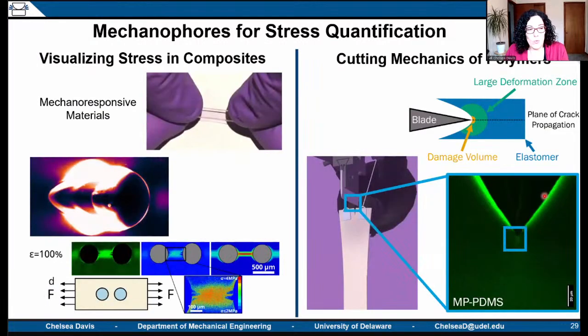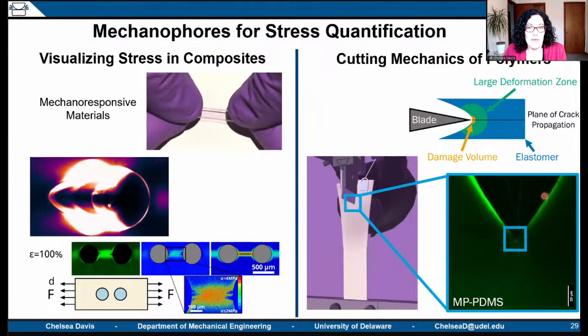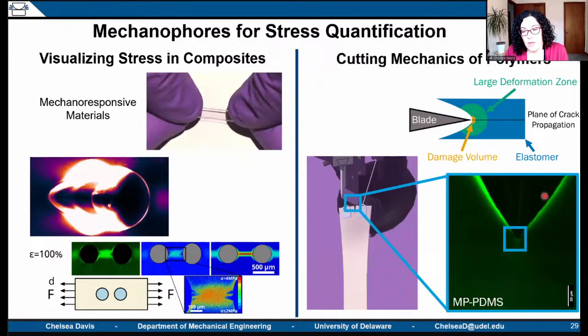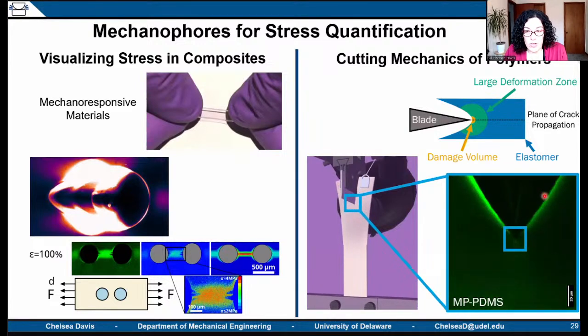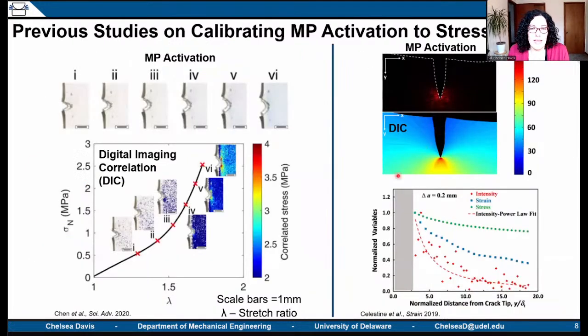All right, so with that, I do want to take a couple minutes and tell you about the cutting tools that we've been developing in my lab that allow us to observe mechanophore activation ahead of a propagating crack tip. So if you'll remember, at the very beginning of this talk, I motivated with this idea that calibration has been performed at the stress concentration that occurs ahead of a propagating crack tip. In our materials, our silicones specifically, that are too brittle to allow for spontaneous crack propagation, we haven't been able to observe this stress concentration because the crack propagates too quickly through our material.